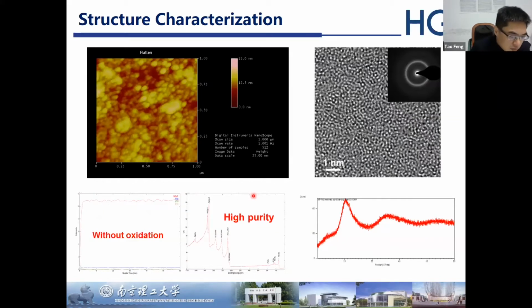We did a lot of structural characterization on this electrodeposited nickel phosphorus nanoglass. This is XRD, and this is high resolution TEM. From these results, we can see the material has a well amorphous structure. The AFM shows a traditional nanoglass feature on the surface, which is the nanograin structure. And from XPS, we can see its high purity and no oxidation. Please keep in mind, this clean surface is very important for understanding the nature of nanoglass.